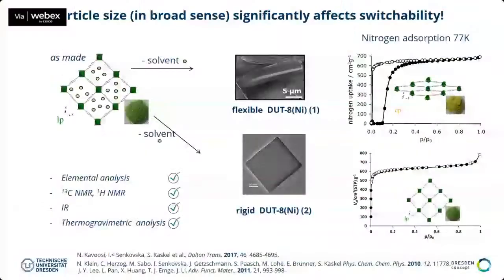Yeah, this is basically by synthesis. So we have different synthesis recipes. Here we get very large crystals, here we get small crystals. In the synthesis, what you often do is, if you have a very high supersaturation, then the nuclei become very small and very many at the same time. And this allows you to make nanoparticles. So in this case, we use an excess of the DABCO for the synthesis, because this way you deprotonate the carboxylic acid and you get a very rapid precipitation. And that's the trigger to make the nanocrystals.